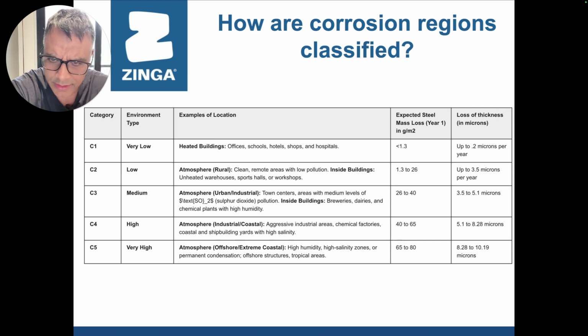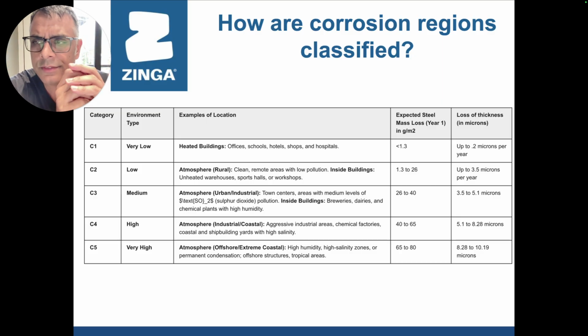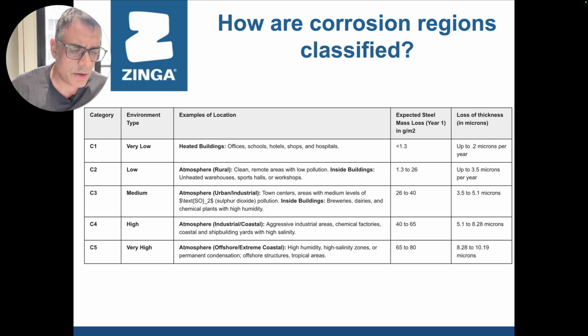C4 becomes even high, where aggressive industrial areas, chemical factories, coastal areas. So I have seen most of the solar sites are between C3 and C4 and C4 and C5. And 8.5 microns a year is getting lost. And finally, very high corrosive environment where it goes up to even 10 microns a year. Now, this is very alarming, but this should not be surprising. You are seeing that in extreme environments the rate of corrosion is much, much faster.